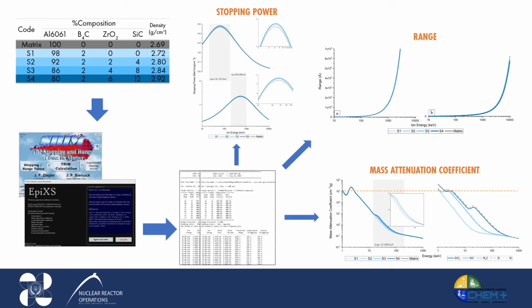The range of both charged particles to the composites is almost similar due to the minimal differences in their densities. The distance traveled by the particle before coming to rest increases as the energy of the particle increases. The MAC shows the different attenuation coefficients of the reinforced composites as a function of photon energy. Most of the interactions are due to the presence of zirconium oxide and silicon carbide.